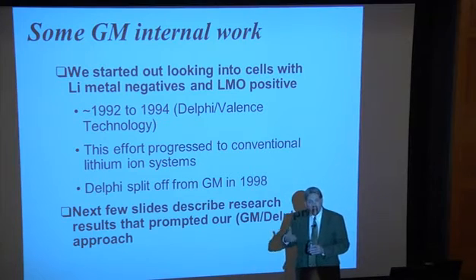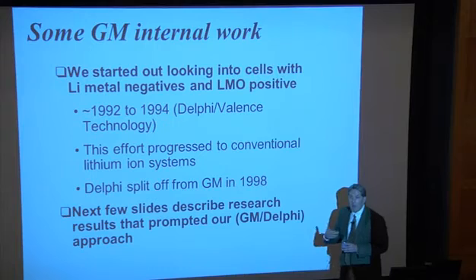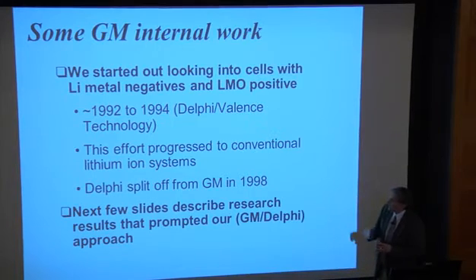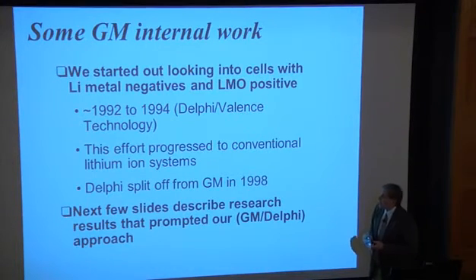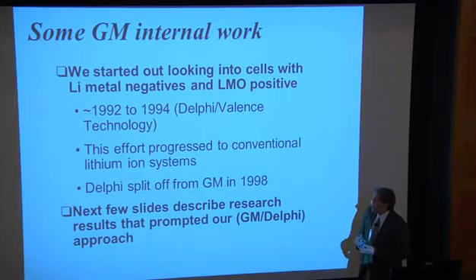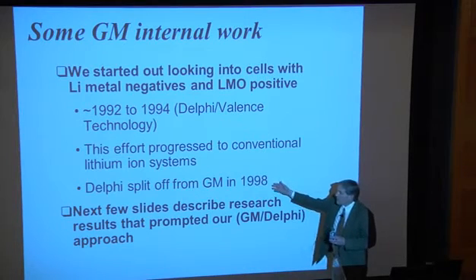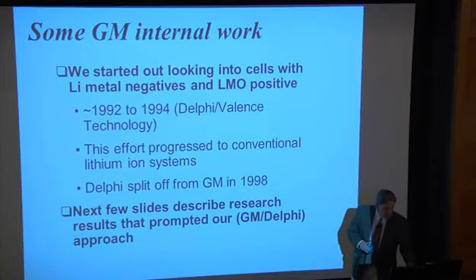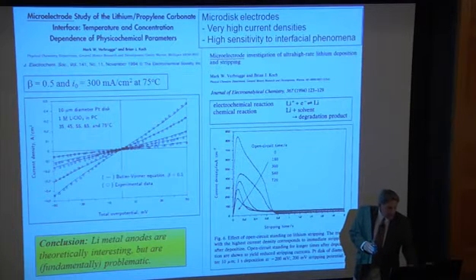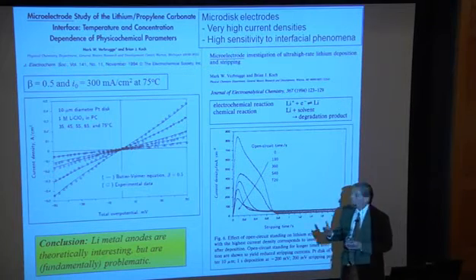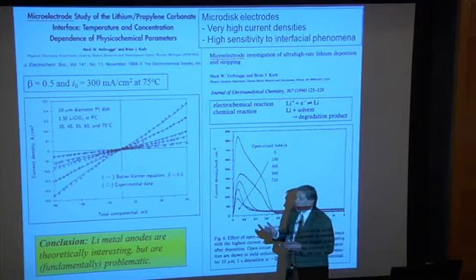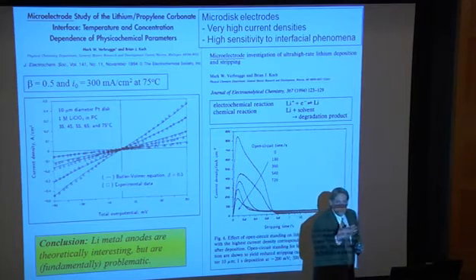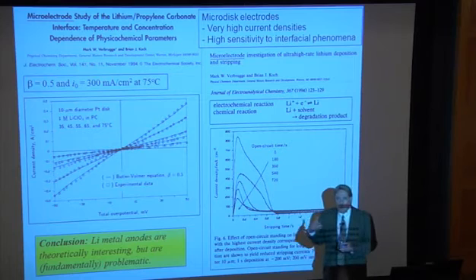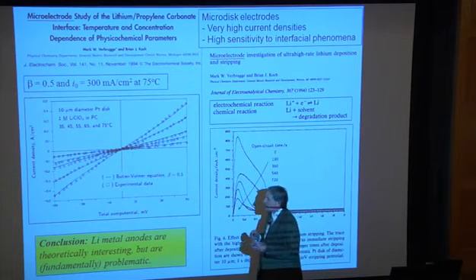GM used to have Delphi, the components group, and so they had a lithium-ion battery starting about 1992. And for about 2 years, we were using lithium metal, and that came to be problematic. And eventually, Delphi was split off, so we didn't go too far down this path together. But when we were doing that work, we tried to do some work that allowed us to understand how these systems were behaving. And I'll show you the results in the next couple slides.